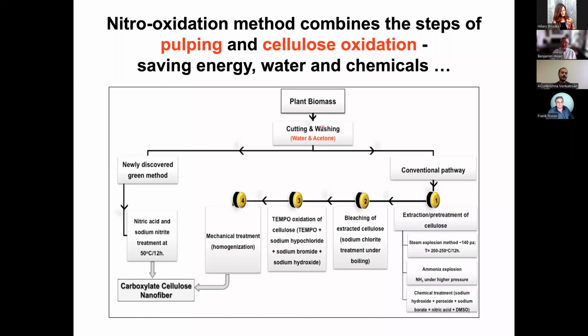So compare with the typical TEMPO oxidation method. This is the conventional pathway. First, you pulp the materials, you bleach them, you carry out the TEMPO oxidation, then mechanical treatment to get nanocellulose. The unique feature of this nitro-oxidation method is we're using fertilization chemistry, nitric acid, sodium nitrite. Just a one-step treatment, maybe a very mild mechanical treatment, we can also extract carboxylated nanocellulose. Carboxylated is important because it's negatively charged and will stabilize these materials in suspension.